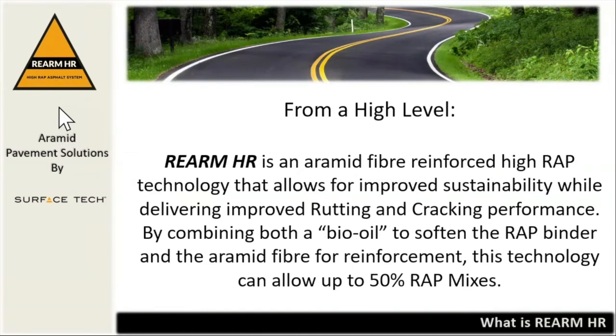Thanks. Another new solution from Surface Tech is REARM HR. In order to maximize the amount of RAP that can be used in an asphalt mix, REARM HR has been developed to use a combination of aramid fiber and bio oil to create a mix design that achieves specific performance targets. Using a balanced mix design approach, local aggregates and binder, including the RAP, are used to create an asphalt mix design that matches or exceeds the performance of a traditional low RAP mix while using a much higher RAP content.